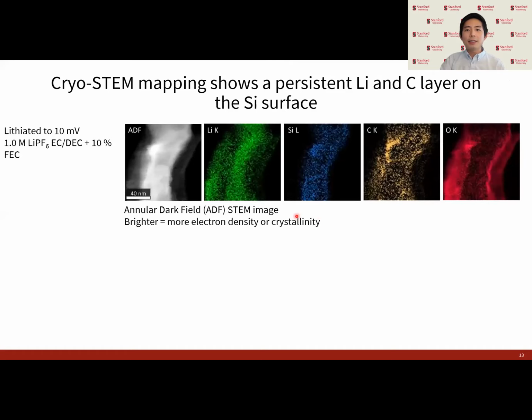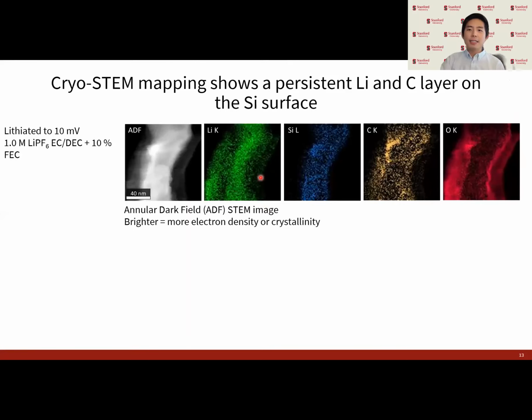And we can again do the STEM EELS mapping and see that a dense, thick, organic-rich SEI is forming on the silicon nanowire surface. And notably, there isn't really any fluorine in this SEI, which further reinforces that the defluorinated FEC is polymerizing into a poly-VC polymer onto the silicon surface.